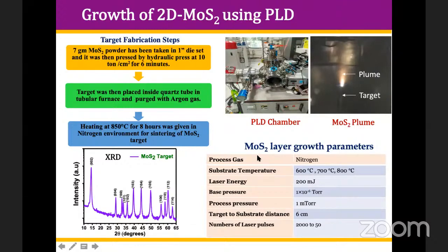You can change the ambient because there is no oxygen. So I'm using the non-reactive inert gas nitrogen in the chamber. And then the substrate temperature can be varied from 600 to 800. Even you can change, it's up to your choice, but I'm changing from 600 to 800.